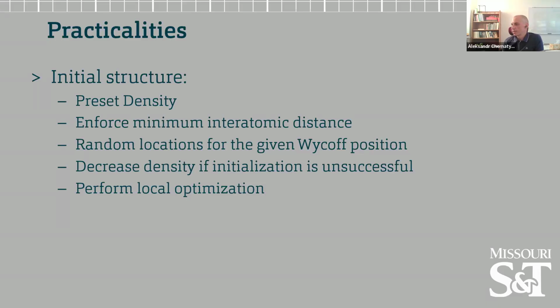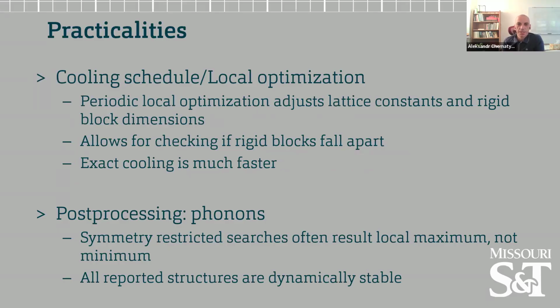This is something which is kind of hard to include in the general discussion of how the system is working, but one always has a tool of doing local optimization from any given point. What we're going to do throughout our simulation is periodically run a local optimization in order to mitigate maybe this effect of not being able to cool sufficiently slowly. We periodically perform local optimization in order to settle down our structures and see where we are. And that also allows us to check if the rigid blocks actually fall apart or not. In all our experience so far, we had only one system where the rigid blocks started to fall apart on us. So we think it's reasonably applicable.